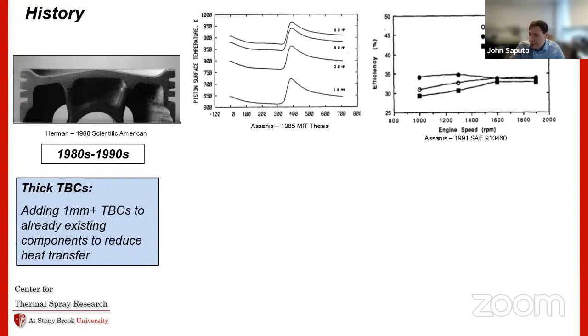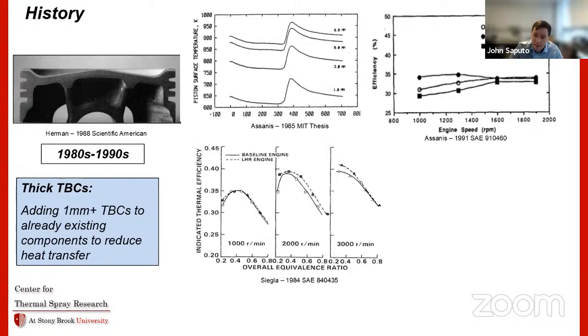So you can see this performance testing again shows interesting results: using a thinner ceramic actually performs better than a thicker ceramic. So this is telling you that even though you have a higher insulation capacity from these thick ceramics, they perform worse. And that's partially due to the reason I mentioned, the heating of the intake gases.